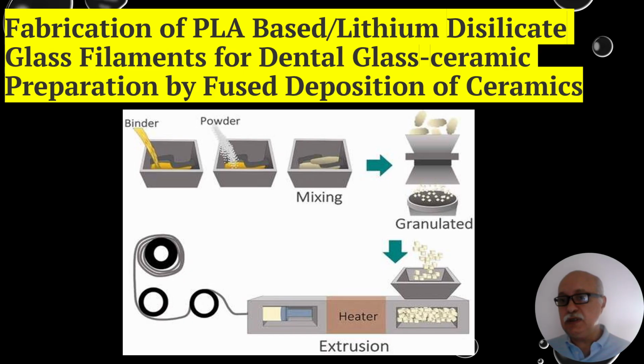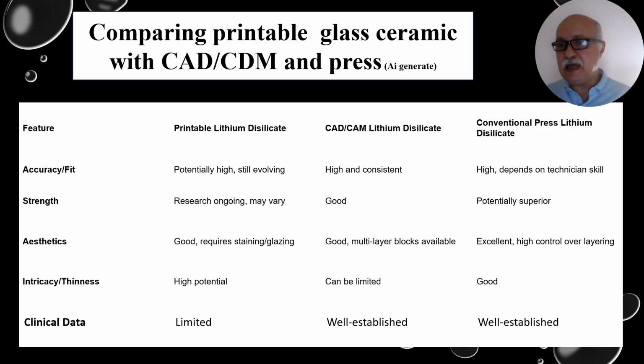The 3D printing of ceramic is expanding more and more every day. Filament fused deposition is a simple and well-established method which is currently available for lithium disilicate. In comparing printable and conventional glass ceramic, I should say in terms of fitness and aesthetics there shouldn't be any problem. Regarding strength, conventional methods are supported by strong data and documentation, while 3D printing does not have enough data. As I mentioned, 3D printing may be preferred for preparing thin restorations.